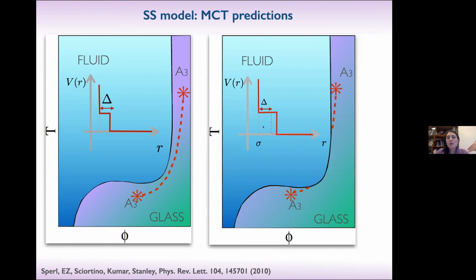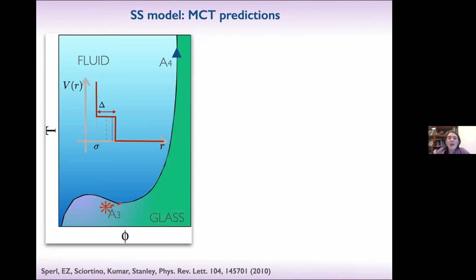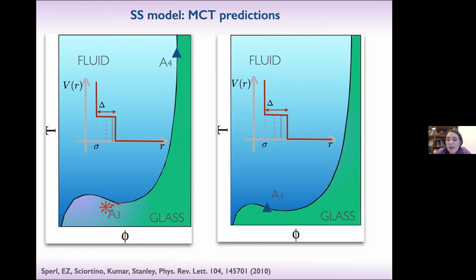And then, as we did in the square well, we can always play with another parameter, that is the width. And as you change the width, then these lines move closer to the liquid-glass ones. And then you have two distinct glass lines with two distinct A3 points. And then if you continue, as we saw before, one of these merges first, you have an A4 here. And then you continue to increase the width, you have another here, and you have another A4.